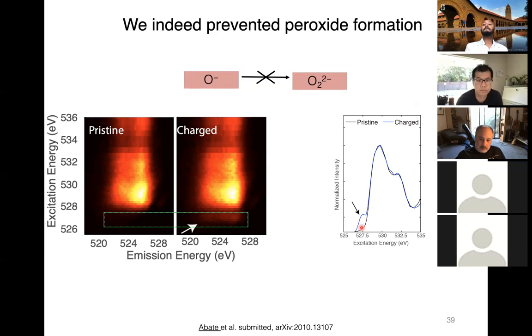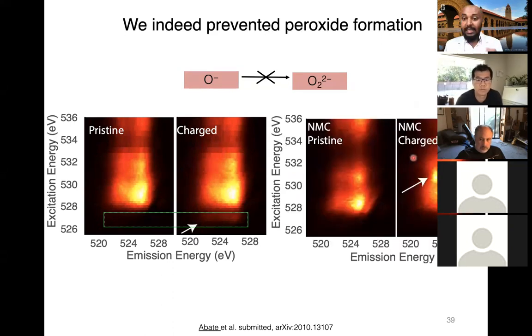And this is obviously very different from what you observe in the NMC material, where we have the hysteresis, where you have this feature coming close to 531 eV, but this one is 527 eV, indicating that we're not forming a peroxide in the sodium manganese system. We are forming a new species over here, which might indicate that we are forming the O- species.